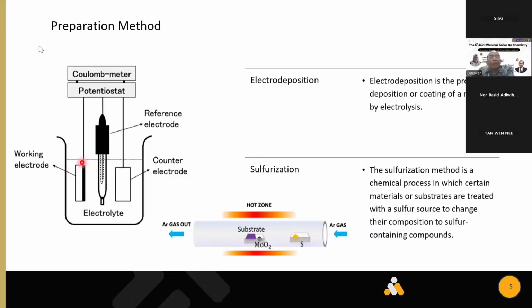And this is the way to prepare it. As I stated before, for preparation of copper indium sulfide, just like my student now works on, we can prepare it using spray pyrolysis. We can spray copper indium sulfide onto a molybdenum substrate on glass. We can also use other processes. But the electrodeposition process is very simple. And as far as I know, electrodeposition is very good for producing copper indium sulfide with good efficiency.